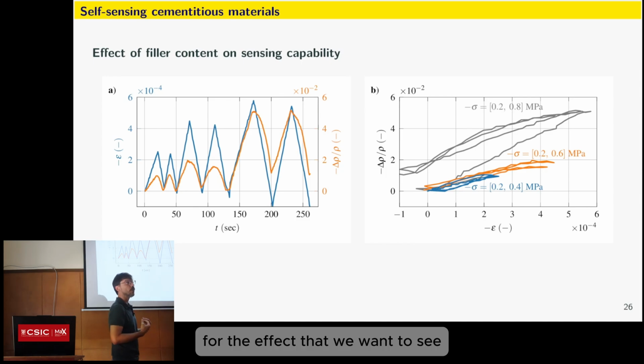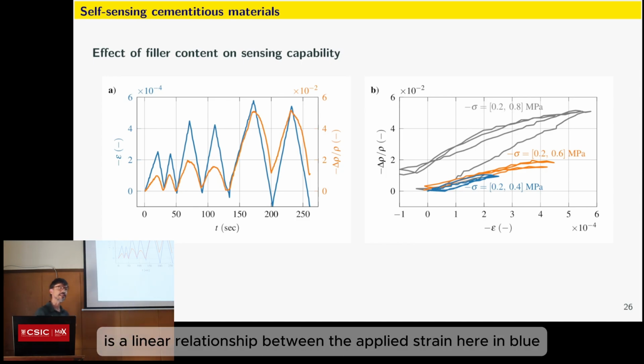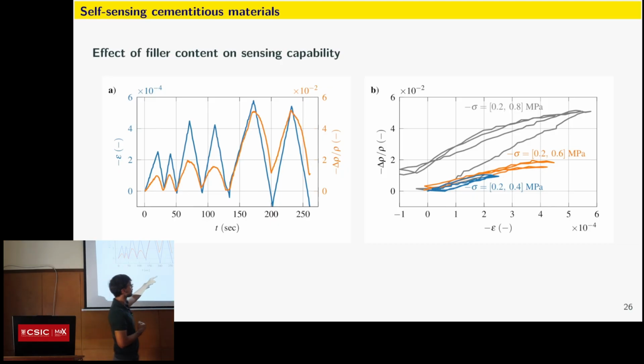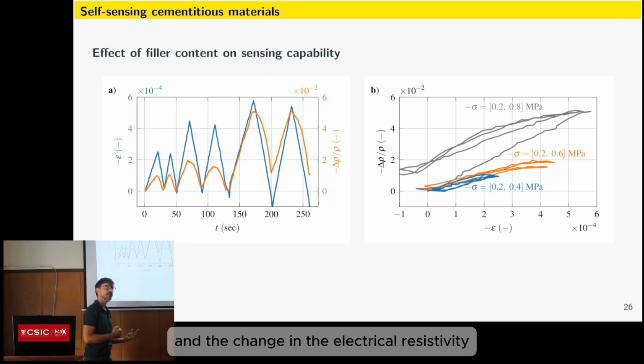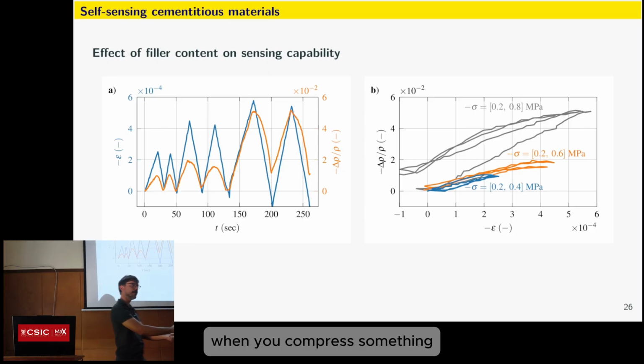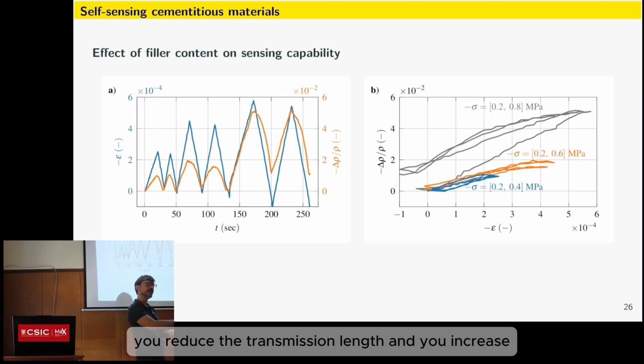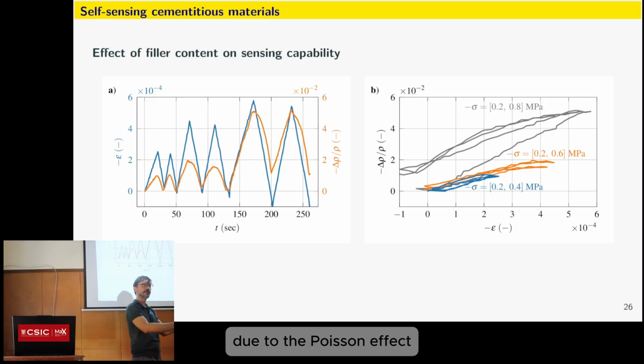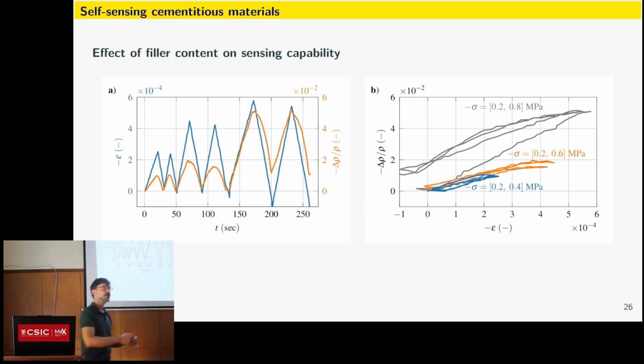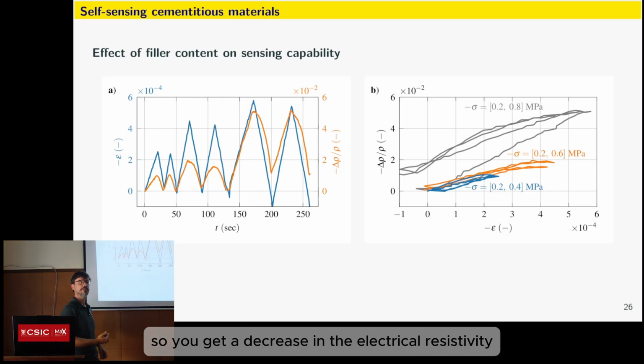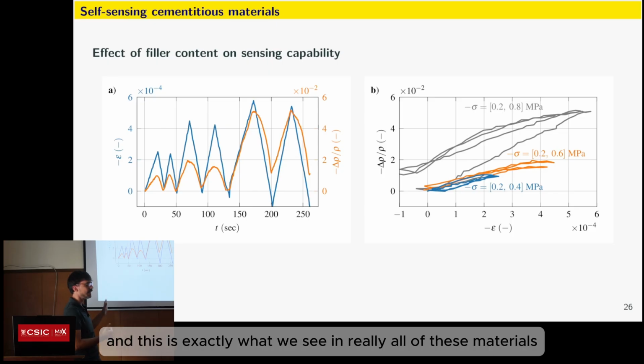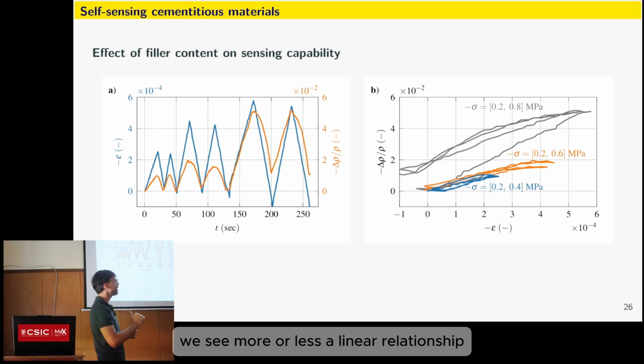So the effect that we want to see, really, is a linear relationship between the applied strain, here in blue, and the change in the electrical resistivity. When you compress something, you reduce the transmission length, and you increase, due to the Poisson effect, the transmission area, so you get a decrease in the electrical resistivity. And this is exactly what we see in really all of these materials. We see more or less a linear relationship